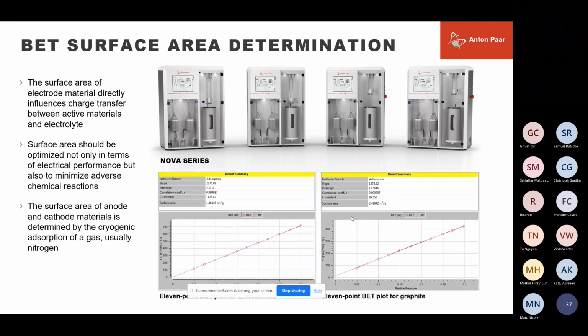So specific surface area, also referred to as the BET surface area, after the three scientists that developed it, Brunauer, Emmett, and Teller, is probably the most critical physical property for battery electrode material. This method uses gas sorption data to quantify the number of molecules of adsorbate on a monolayer of the surface of the material in order to determine the surface area in square meters of the sample. And the measurement is done in a very specified relative pressure range from 0.05 to 0.3.